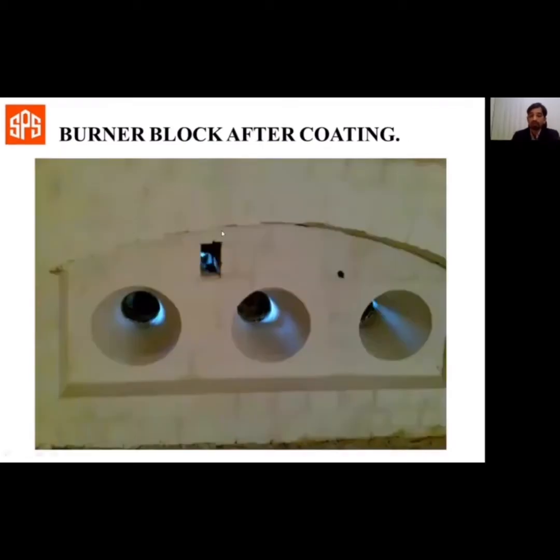Here, you can see the smooth finish achieved by the use of refractory coating on the same furnace. All gaps and cracks are sealed off, thereby preventing energy leaks. S.P.Shenoy refractory coating can withstand up to 1900 degrees Celsius. It is highly resistant to thermal shocks and cracks.